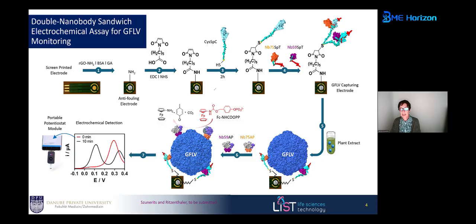And the chemistry we like currently very much is integrating first Cys-SpyCatcher modified structures on these maleimide modified interfaces, where then we can interact very easily, like in a biotin-avidin interaction concept, with SpyCatcher ligands. The main difference with biotin-avidin is that the KD is almost the same. But if we would translate it to humans, for sure, we don't have any SpyCatchers in the body. Biotin we would have, and even in high concentration. So there could be an equilibrium between the bioligand attached to the surface and biotin in the blood, which would actually take off the ligand. Fortunately, this is not the case in plant viruses, but that's only an example.